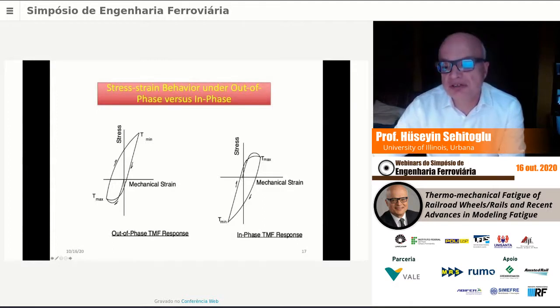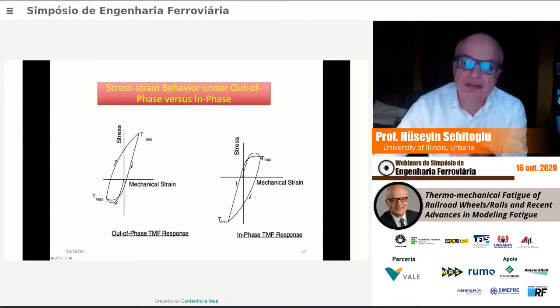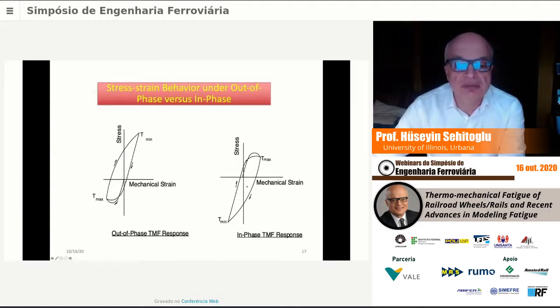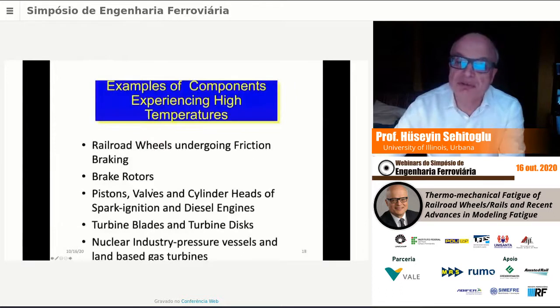The in phase case is just a flip flop opposite of that, right? So you're hot in tension and you're cold in compression. And you can see there's a tensile mean stress here. There's more of a compressive mean stress here. But of course, with your high temperatures in tension, this is more prone to creep damage, while here you're hot in compression, and this is where you potentially form the oxides, and then the oxides can break when you go into tension. So there could be different damage mechanisms in out of phase versus in phase.